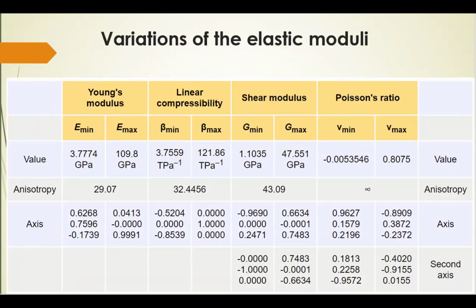Using the second-order elastic constants obtained in this study and the ELATE interface, the three-dimensional behavior of the polycrystalline moduli was estimated. A high degree of orientation dependence was observed in elastic moduli. Young's modulus and linear compressibility have about 30 times anisotropy, while shear modulus has around 43 times. Also, Poisson's ratio has the highest anisotropy among the other moduli. It varies between 0 and 0.81 depending on the orientation.